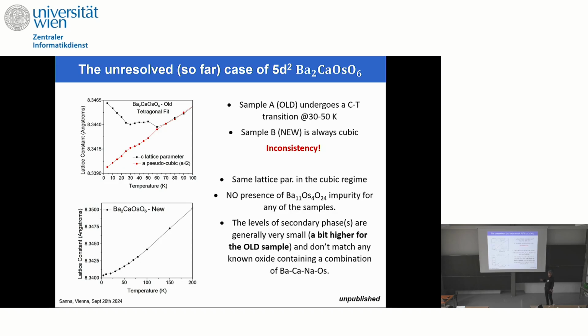Why for this sample is it still cubic? The two samples have the same lattice parameters, no presence of typical impurity in either sample, at least within the limit of detection of high resolution X-ray diffraction. The level of secondary phase is generally small, a little bit higher for this sample, not that much. And they don't match any non-oxide containing combination of these. So formally they are the same samples.